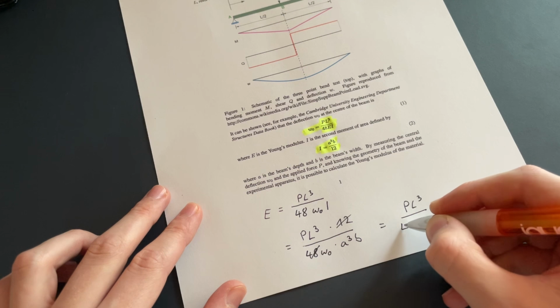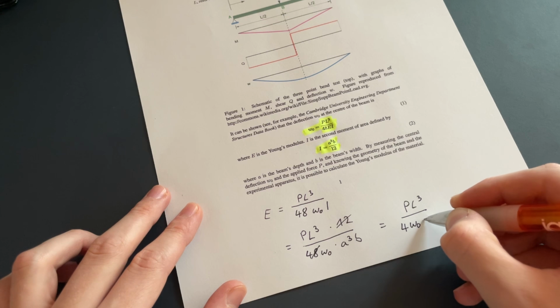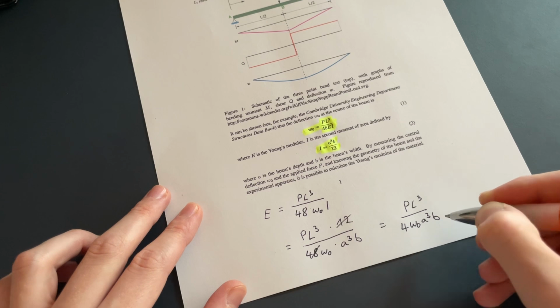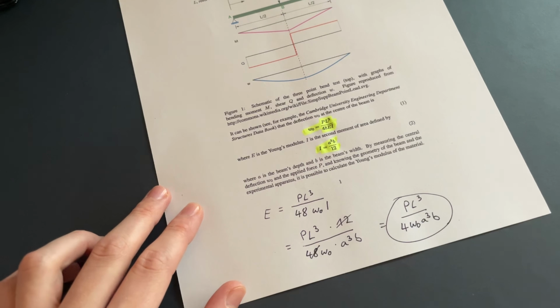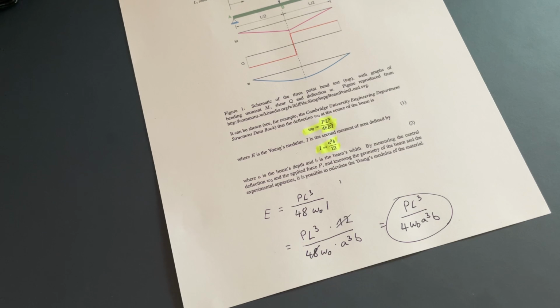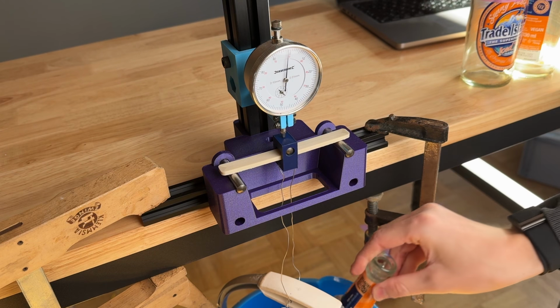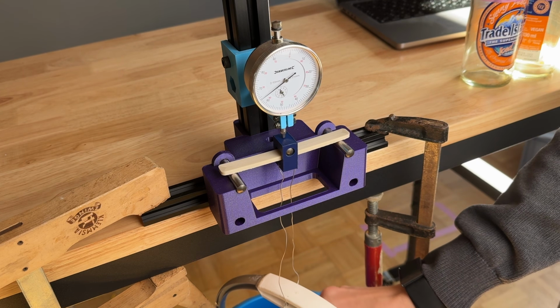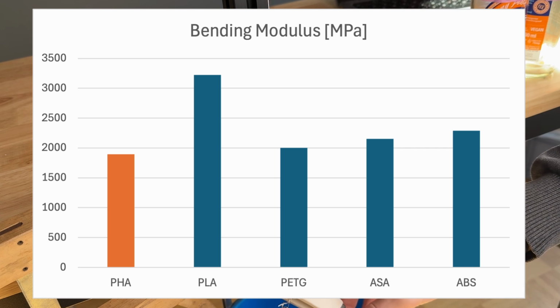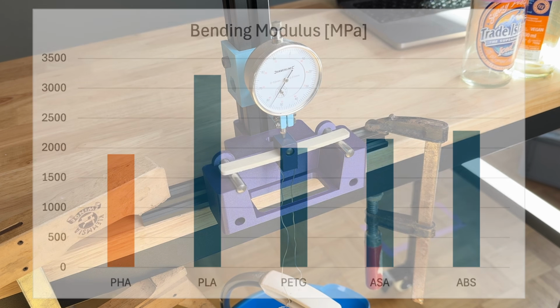The bending modulus in megapascals can then be determined using a formula based on the deflection and the surface moment of inertia. The higher this value, the stiffer the material and therefore the less elastically deformable. I came up with a bending modulus of about 1900 megapascals, and the comparison shows that the stiffness of PHA is similar to that of PETG. Compared to regular PLA, this is relatively low, yet totally fine for most applications.